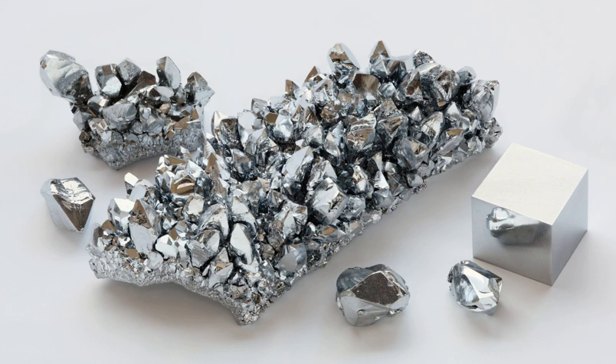Chromic acid anodizing or type 1 anodizing of aluminium is another electrochemical process, which does not lead to the deposition of chromium, but uses chromic acid as electrolyte in the solution. During anodization, an oxide layer is formed on the aluminium. The use of chromic acid, instead of the normally used sulfuric acid, leads to a slight difference of these oxide layers. The high toxicity of Cr(VI) compounds, used in the established chromium electroplating process, and the strengthening of safety and environmental regulations demand a search for substitutes for chromium or at least a change to less toxic chromium compounds.